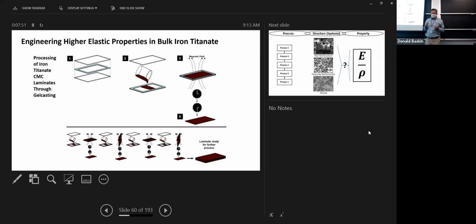Okay, and then if you can burn out the acrylic, compact the material and sinter it, it's a ceramic, right? So it sinters. Then you'll have a quasi-single crystal. It's not really a single crystal because it's got grains, but the grains are aligned, which is called a crystallographic texture. That crystallographic texture means that it has different stiffnesses in the three different directions. So there's an example where you've engineered the stiffness of the material.